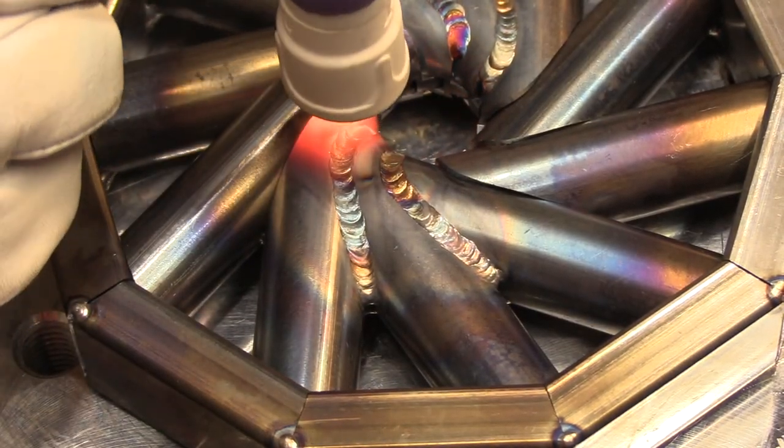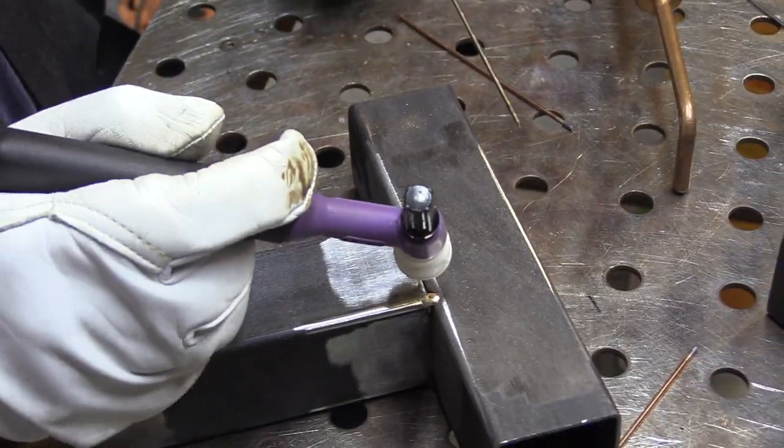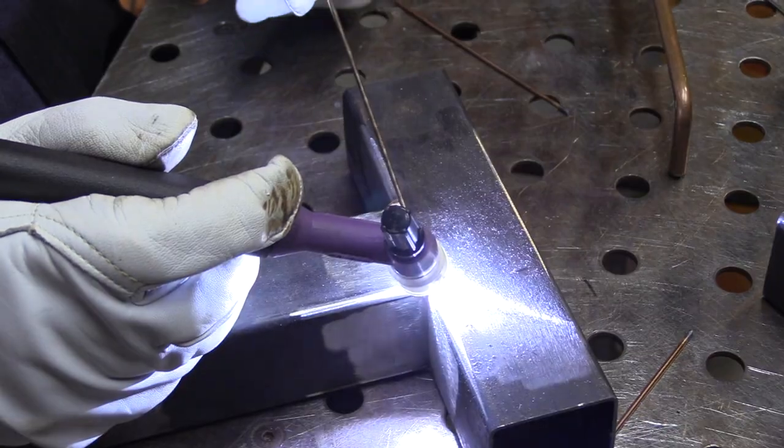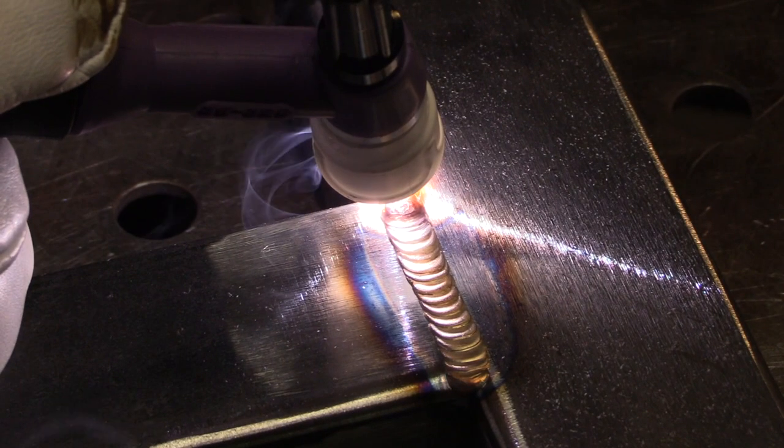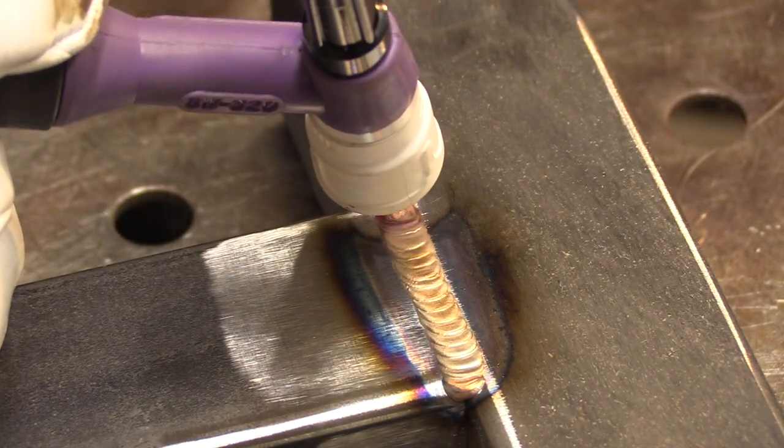This is cold rolled steel, but I'm using silicon bronze filler metal and look at that big argon shielded area. It's just about a perfect size cup for TIG brazing with silicon bronze or aluminum bronze. I like to use two pulses a second, actually one and a half to two pulses a second. I've found works great. You need your metal clean and you also need a really good argon shield and you'll get it with the Jazzy 10.